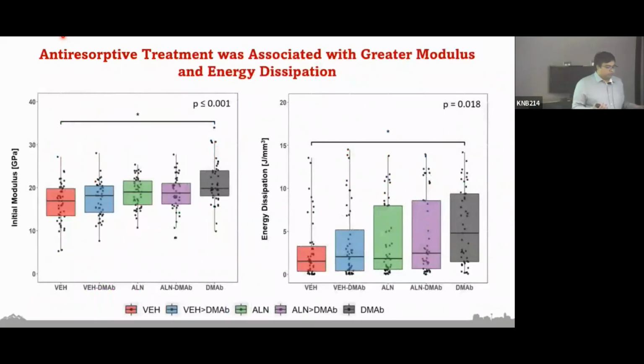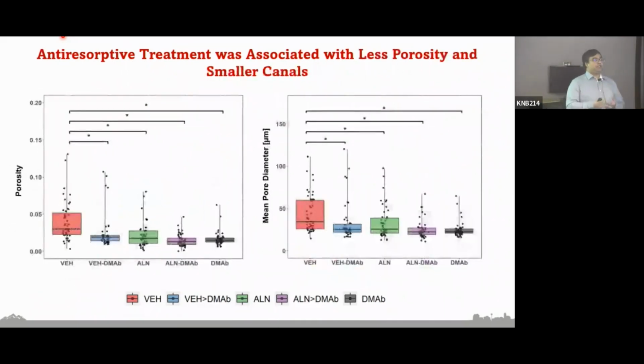Follow-up measures all sort of supported those fatigue life findings that we saw. In general, we saw higher initial modulus in the denosumab group, as well as, surprisingly maybe, more energy dissipated, not less, in the denosumab-treated animals. We also saw our micro-CT was really consistent. It's nice because you don't always get measurements that are so consistent with each other, but we saw that all of the antiresorptive treated animals had lower porosity and smaller size of individual pores compared to vehicle.